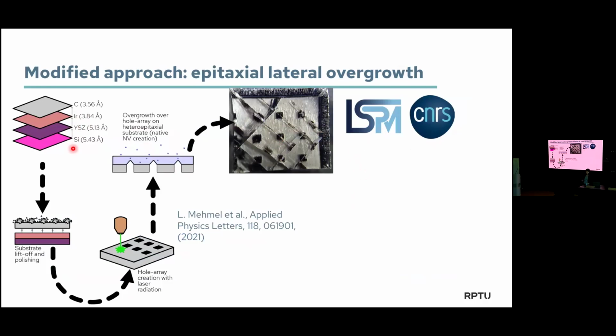They have some kind of a sandwich layer. So they're growing this diamond on iridium. The iridium has almost the same lattice constant as the diamond. They do this diamond growth. They call it heteroepitaxy. And now we know that this heteroepitaxial material is not as good as the one that's been grown on a diamond. But to make this better, they use this heteroepitaxial material, they drill holes in it with a laser cutter, and then they grow again.